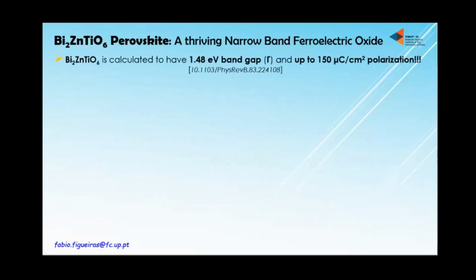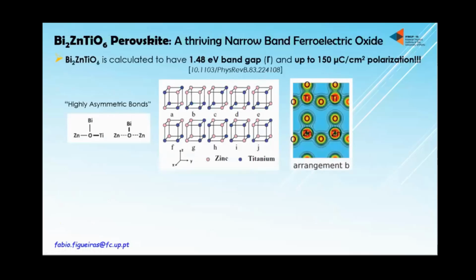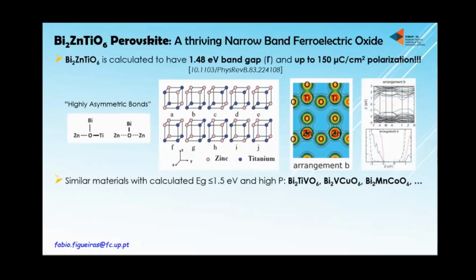So I go for another material, bismuth, zinc, titanium oxides. This material makes highly asymmetric bonds between zinc and titanium. The arrangement of charge will be very displaced, meaning that it promotes ferroelectricity and very high polarization. And the band gap is below 1.5 electron volts. These other materials are also possible, but zinc and titanium are more accessible than vanadium, for instance, and much easier to handle in production.